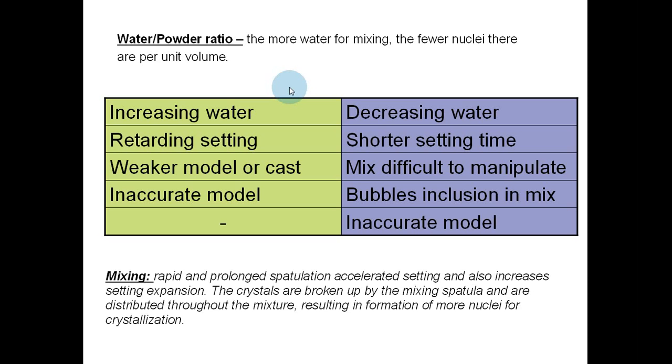Mixing. Rapid and prolonged spatulation accelerates setting and also increases setting expansion. The crystals are broken up by a mixing spatula and are distributed throughout the mixture, resulting in formation of more nuclei for crystallization.